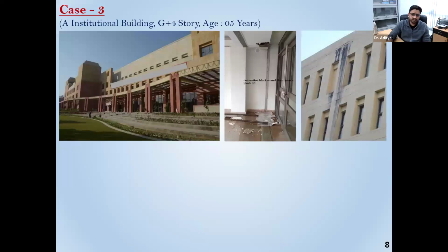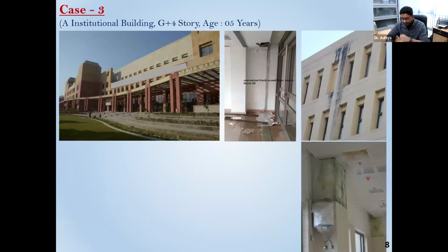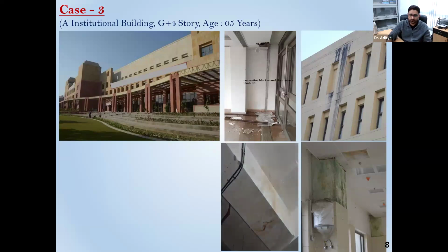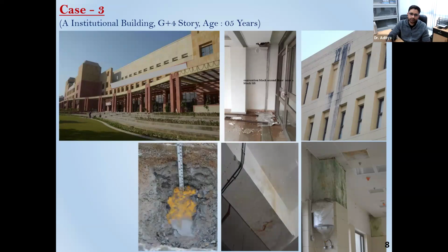You can see the water was dripping continuously all along the periphery, which was actually causing the structural members to start to distress, because obviously if there is seepage throughout the year, there are very high chances that the RC elements, be it beam, column or slab, will start to corrode, and that's what was going on all along the structure. So upon doing all the investigation, the main finding in this particular structure was that the quality of construction is good. The maintenance is also fine. The only problem was that the waterproofing treatment they did to the terrace was not good enough.